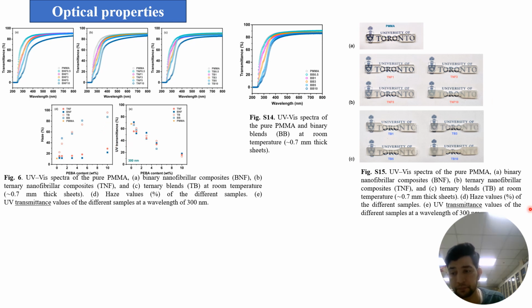So in the next graph, figure 6e, the UV transmittance value decreases significantly as the PEBA concentration increases from 0% to 15%, up to 10% PEBA, for all systems. However, at low concentration, up to 3% or less, the drop was lesser, with the TNF exhibiting a UV transmittance of 45% at 300 nanometers.